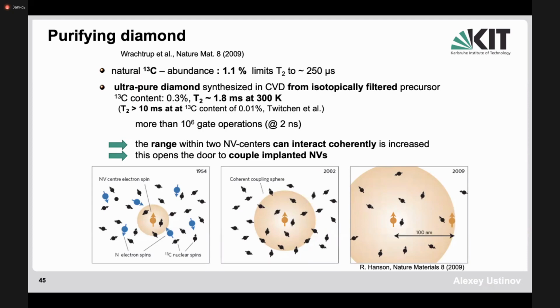Simply because the system is very unharmonic, and you could drive it very, very hard and make the Rabi flopping very, very quick. So the range at which these defects can interact without being distorted by impurities, of course, increases, but you need really to bring them close enough, and this people try to do by implanting. Nevertheless, having the separation of about a micron, which is feasible for implanting, still leaves quite small strengths of the interaction, which is still kind of unsolved problem until now.